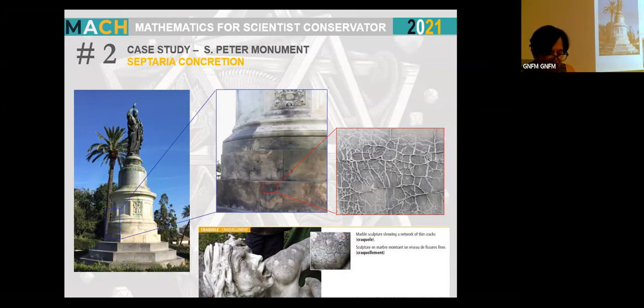It is a chemical-physical degradation represented by a dense network of fissures or cracking from which emerge carbonatic concretions, but which could also contain lead and copper salts transported by water. At a glance, the morphology seemed to recall the crackle, or network of small cracks, also described by the ICOMOS glossary of degradation forms. The origin of cracking can be different, such as weathering, defects in the stone, static problems, rusted iron inserts, too hard filling mortars, or even vibrations caused by earthquakes.